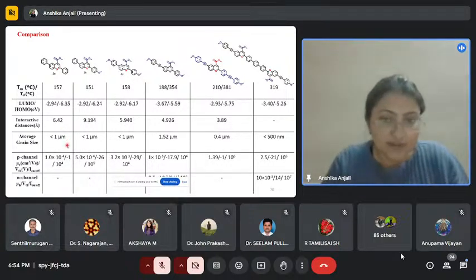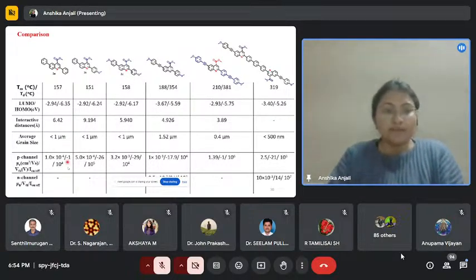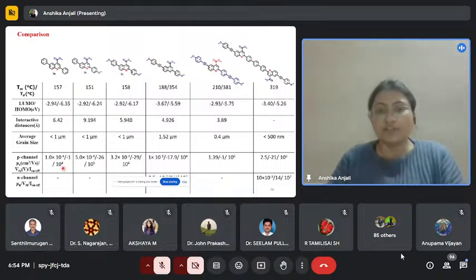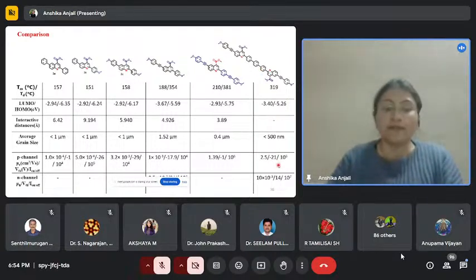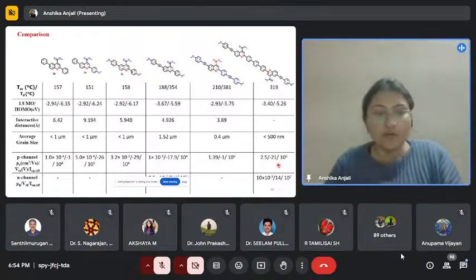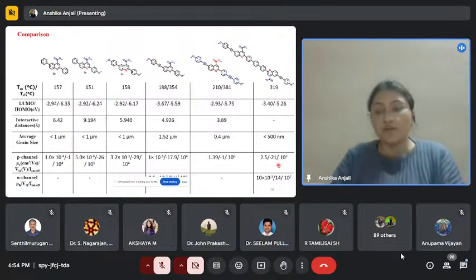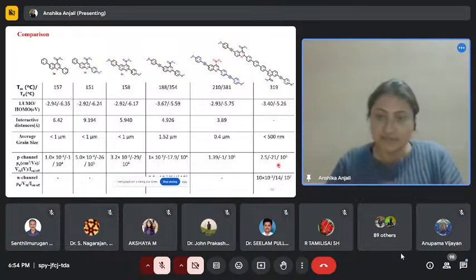Their average grain size values were also calculated, and with increase in the conjugation, from simple phenyl as end groups to the 4-methoxyphenyl group, and also with this triphenyl group as a linker, we have seen increase in their hole mobility from 1 into 10 raised to power minus 4 to 2.5 centimeter square per volt per second. So it's a huge improvement.